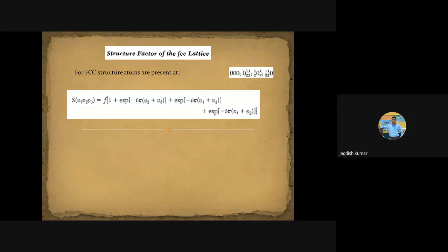Now, what will be the intensity? For the peaks which are to be observed, we have to calculate the atomic form factor as well. Then that will be a complete structure factor. From the complete structure factor, we can calculate the intensity, because from there will follow the scattered wave amplitude, and then amplitude star amplitude will give you the intensity. I hope that is clear. Is this fine till now, or is there any question?